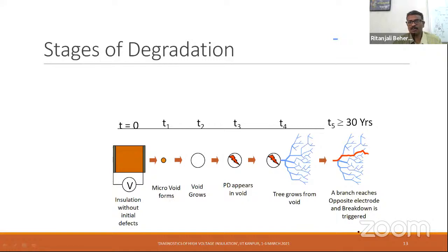So once the first branch forms from the void, it leads to many more branches. Those branches may be conducting, or may be non-conducting also. When it is a conducting channel, the tip of that branch will act like an electrode because of its conducting nature, and that leads to further injecting of charges into the surrounding dielectric, and that leads to more and more channels, and finally the tree branches reach the opposite electrode and the breakdown is triggered. This might take even as long as 30 years as per the reports.